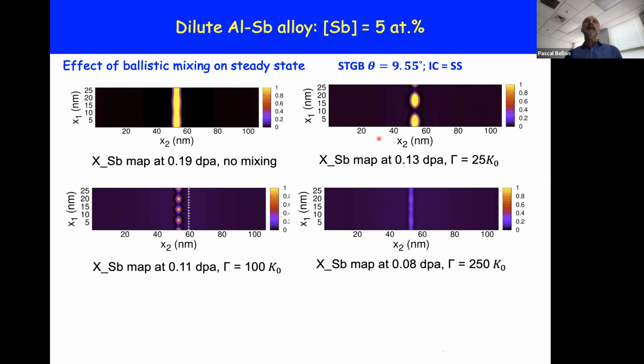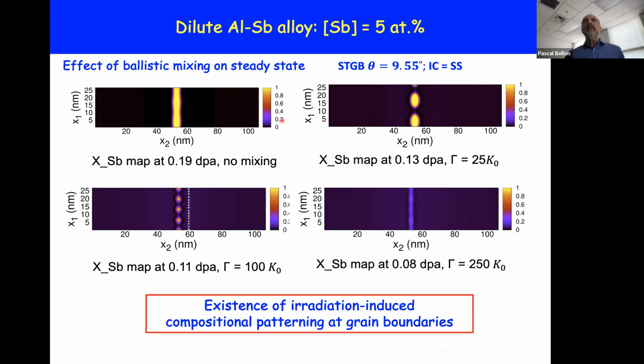When we include the mixing, with a coefficient of 25 or more, at value 100 or even more, when this coefficient goes up to 250, we reduce the amount of segregation, which we expected, but at the same time, it changed the distribution of solute atoms on the grain boundary. You can see here we went from a continuous film to 2 precipitates to 4 precipitates to a very faint continuous film. So it is another example of patterning where the system chooses its own length scale and number density of precipitates along the grain boundary.